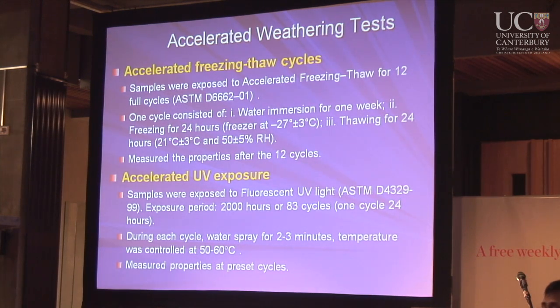Okay, and now, as I mentioned, we also did accelerated weathering tests. We use accelerated freezing and thaw cycles. We put the materials in the freezer for 12 full cycles. Every cycle, we put them in the water for a week, then in the freezer for 24 hours at minus 27 degrees C, and then we thaw the materials for another 24 hours. After quite a long time, after 12 cycles, we measure the properties.